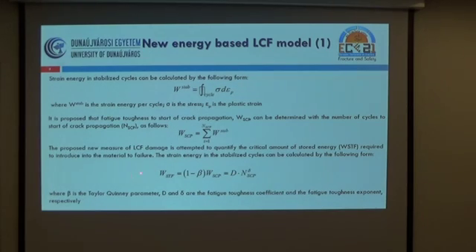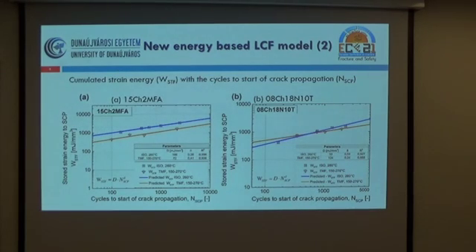And it is written in this equation where the beta is the Taylor-Quinney parameter and the D and the delta are the fatigue toughness coefficient and the exponent. And then some illustration of this energy-based model. And you can see here the stored strain energy, this W stored to fatigue, and the cycles, and you can see both the isothermal and the thermomechanical fatigue curves are quite well. In the case of the austenitic steel, this is the picture of these two curves.